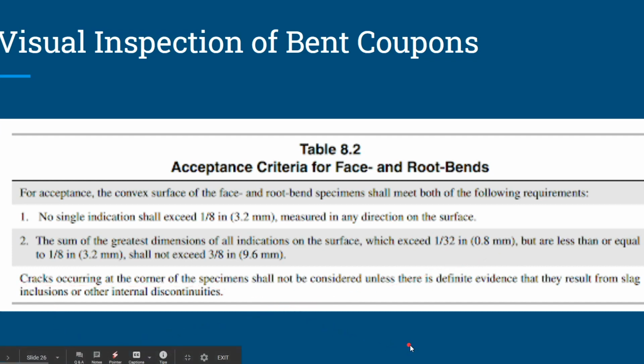Cracks occurring at the corner, however, shall not be considered unless there is definite evidence that they result from slag inclusion or other internal discontinuity. So if you're bending it at the corner of the bend test, maybe it wasn't rounded over quite enough, and it cracks, and you can't see any slag in the crack, or maybe there's a porosity bubble right next to it, or maybe this is more common, lack of fusion like on the root bend where they didn't quite tie into one piece or another, and it starts and cracks from there from the corner down, then it would fail. But if you don't see any of those and it's just a corner crack, okay, it's fine.